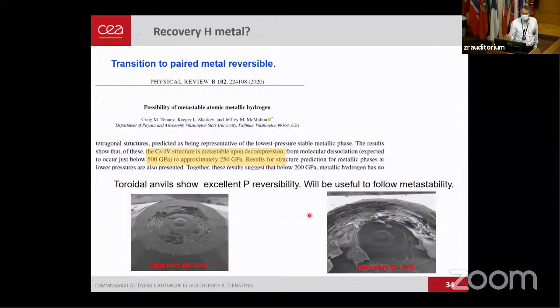Now we have the question of the recovery of metal hydrogen, and the transition to a paired metal is reversible, completely reversible. We recover the hydrogen gas. There has been a long debate since the 70s that probably metal hydrogen, the atomic form of metal hydrogen, could be reversible, could be metastable. The most recent calculations say that you can recover it probably to 250 GPa, but at the lower pressure it could be unstable.